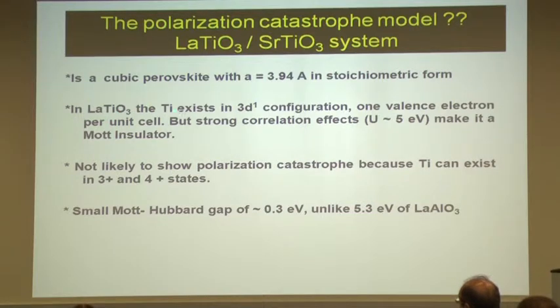And here, the titanium exists in 3d1 configuration. So you have one electron per formula unit. And the standard band theory tells you that it should be a metal, but it is not because of the strong correlation effects. It is a Mott insulator with a Hubbard U of roughly about 5 electron volt.